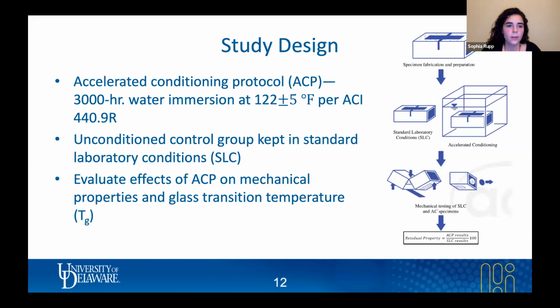ACI 440.9R provides accelerated conditioning protocols, or ACP for short, that provide guidelines on how you can replicate long-term water exposure to a concrete strengthened beam. The two main guidelines to take away from this are that the concrete strengthened beams need to be exposed in water for 3,000 hours, and the water that they're immersed in has to be around a temperature of 122 degrees Fahrenheit. And in order to study the strength retention of these beams that have been exposed to water, we also have to have a duplicated group that is unconditioned or is kept in standard laboratory conditions, or SLC for short. And not only will we be immersing the concrete strengthened beams in the water, but we will also be immersing the constituents that make up the strengthened beam to evaluate the effects of ACP on those materials as well.